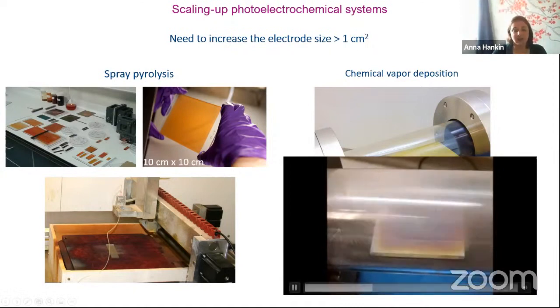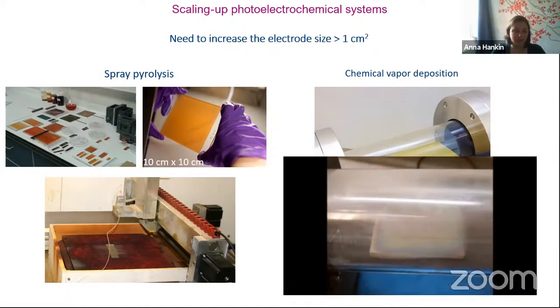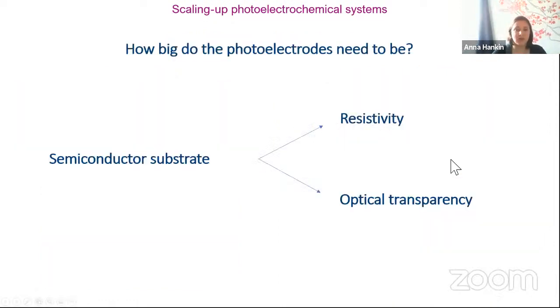So let's say you've managed to make 10 by 10 centimeter super uniform beautiful electrodes. Does that mean problem solved? Does that mean that you basically design a reactor around those systems? Well, not really, because as we're starting to find out, when you have the benefit of transparency, you have some other problems. And one is that this transparent oxide is actually very resistive. So any current that you feed, so electrons that you feed to the semiconductor or take away, they have to flow through this transparent oxide. And because it's quite resistive, it tends to cause losses.